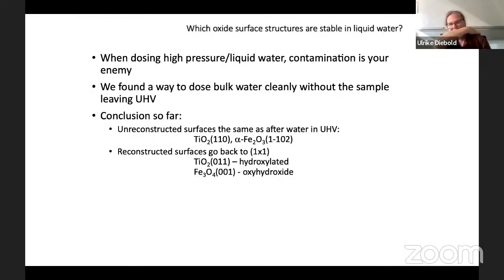We haven't done it that much yet. This is part of the grant that started like last year. Several people that I also saw in the audience are working on this. We try to find out by dosing high pressure liquid water. So first of all, if you dose this high pressure liquid water, contamination is not your enemy but our enemy. As surface scientists, we found a way to do that with clean UHV. So far, what we have looked at is an unreconstructed surface that survives, and then this reconstructed surface going back to 1 by 1. So that's how far we are at.